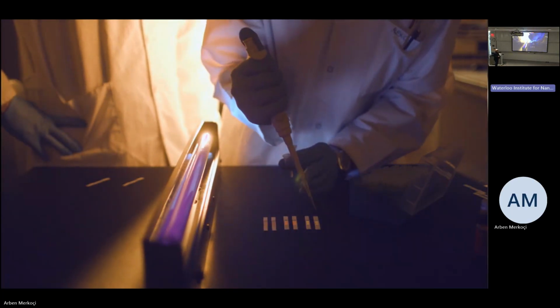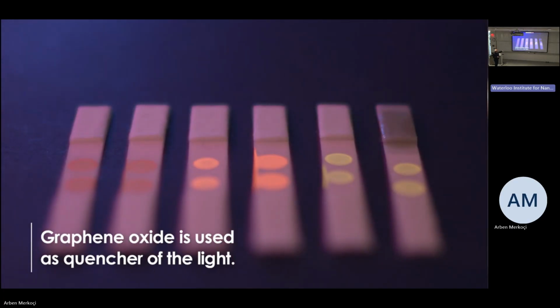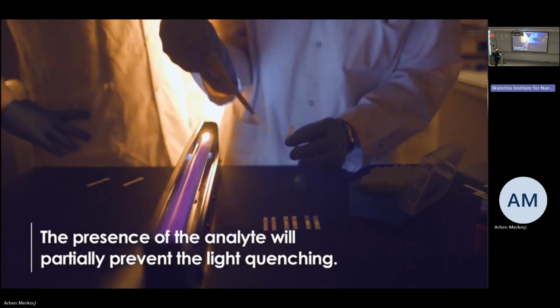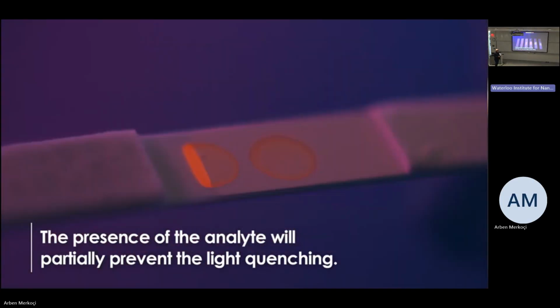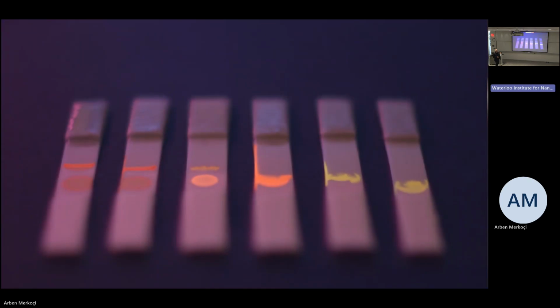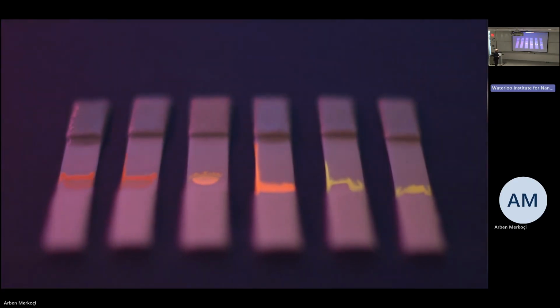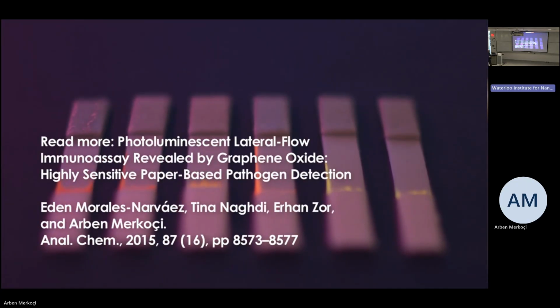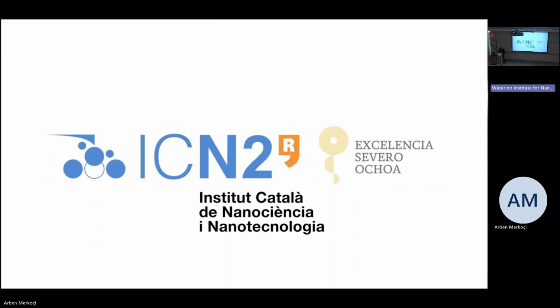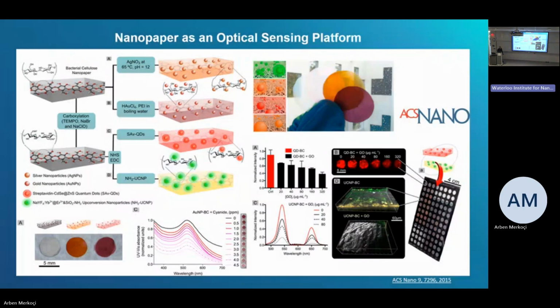Now we are introducing graphene oxide suspension. As I said, due to the capillary forces, this suspension is running across the paper, interacting with the cadmium selenide quantum dots. So the quenching is occurring. And you can imagine that this quenching, driven by the right antibodies, is going to give changes of the color that in turn are correlated with the analyte you want to detect. So after doing the proper correlations, we were able to detect bacteria with this very simple platform.